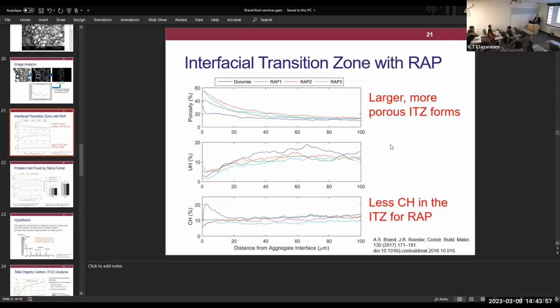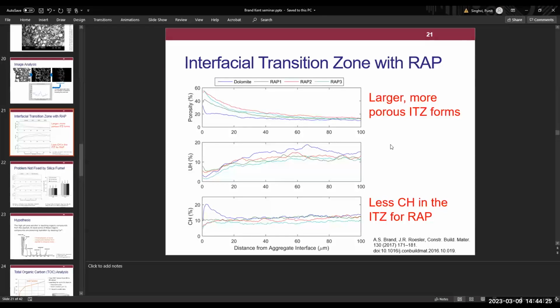One of the things we did find, through the surface free energy measurements, is that the energy of cohesion of the asphalt is less than the energy of adhesion with cement, which means that the crack will propagate through the asphalt film, not through the interface with the ITZ. We were actually able to experimentally confirm that. So that's one of the other reasons we see reduced strength in these behaviors.